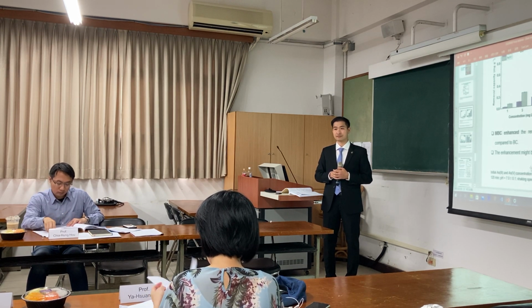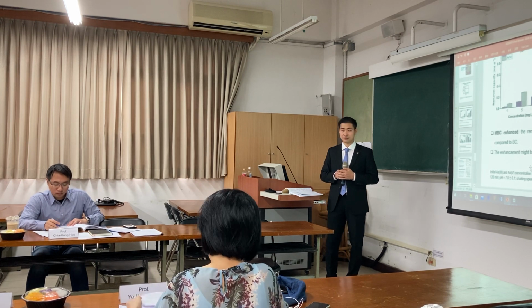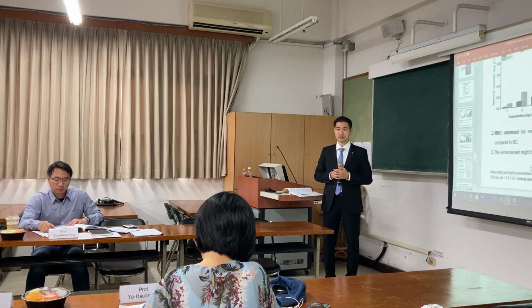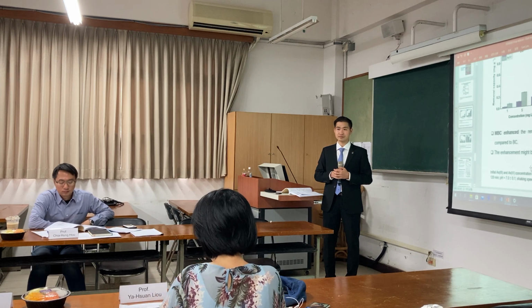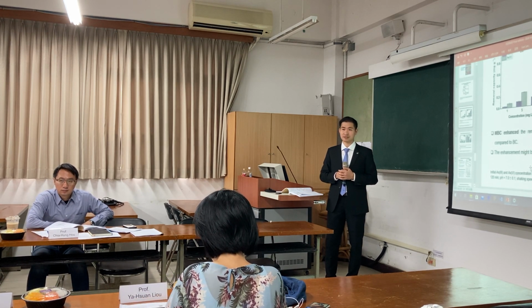And arsenic 3 is neutral, it's set at pH 10. Yes, the pKa is 9.2. Arsenic 5 is negative charge. Yes. So you oxidize arsenic 3 from neutral to arsenic 5 negative charge, and you have a negative charge surface. How can they interact?